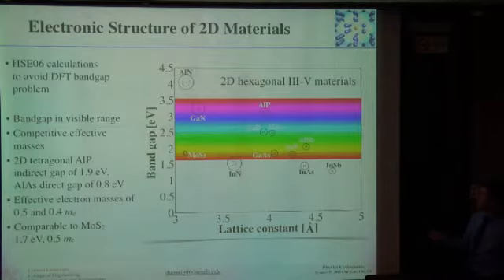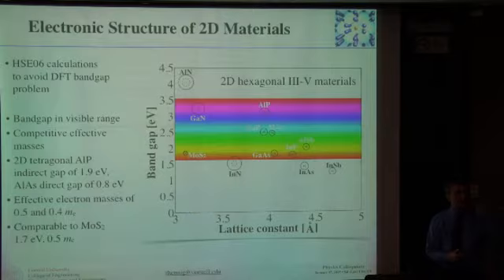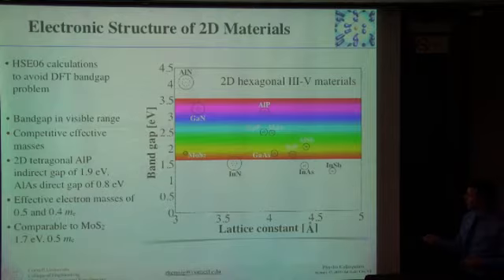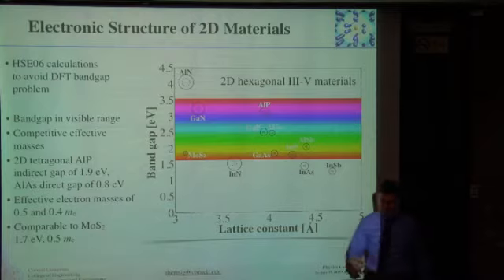And the band gap itself is, of course, important because it tells you a lot of the device properties. And the size of these circles means the effective electron and hole mass. And what it means is you want small circles. Small circles means the electrons and holes have a small effective mass. It means the material has maybe a higher mobility than the materials which have higher effective masses. So things like gallium arsenide in that 2D form are pretty good. Here's molybdenum disulfide just as a reference. That's what's currently used. So some of these have very similar effective masses, useful materials.